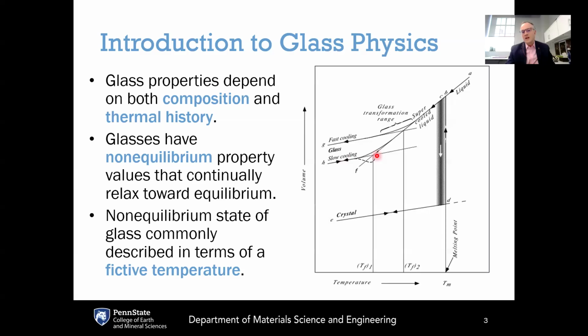structure of the glass. Now, the simplest way to get the fictive temperature is to draw a line that is tangent to the glassy line and then see where that line intersects the supercooled liquid line. For the fast-cooled glass, that intersection point is here. And if you drop that down to the x-axis, this is labeled as TF2. This is the fictive temperature of the fast-cooled glass.